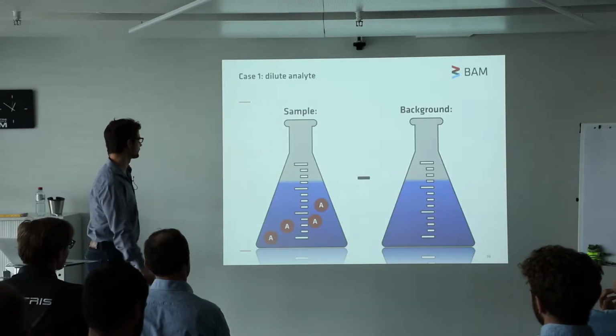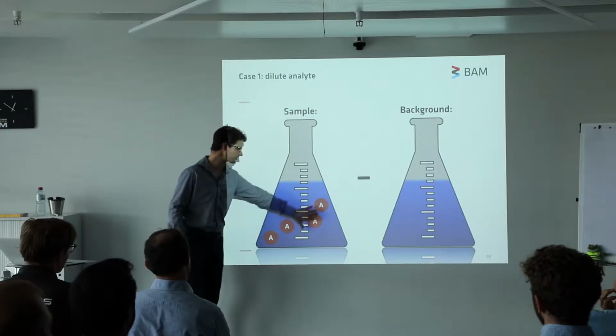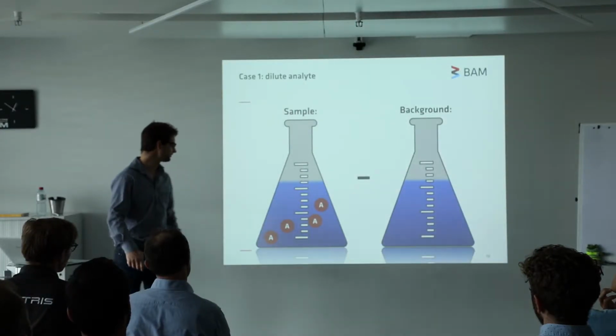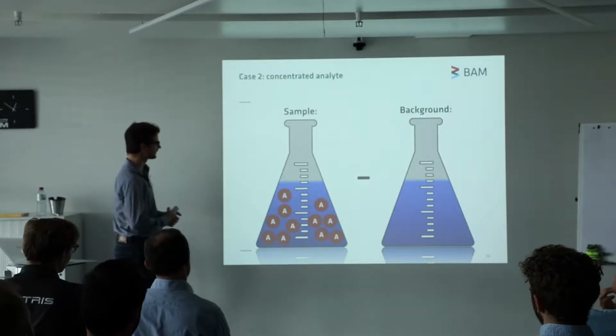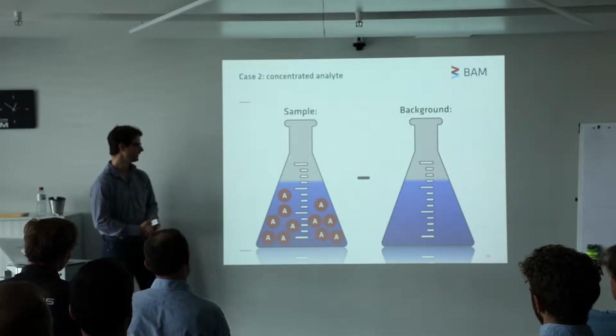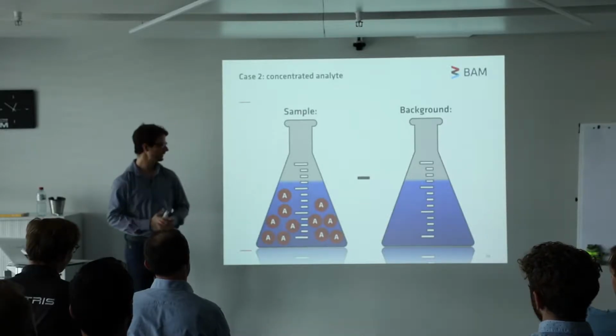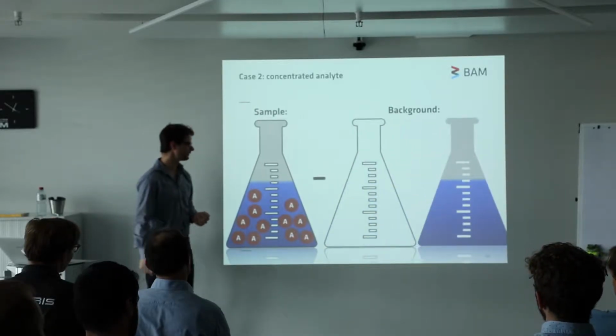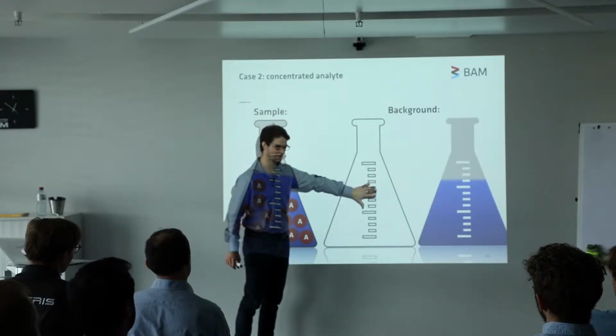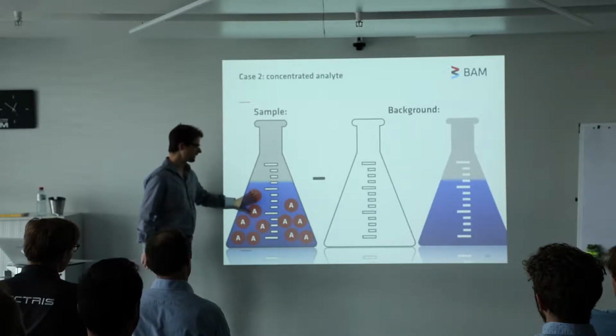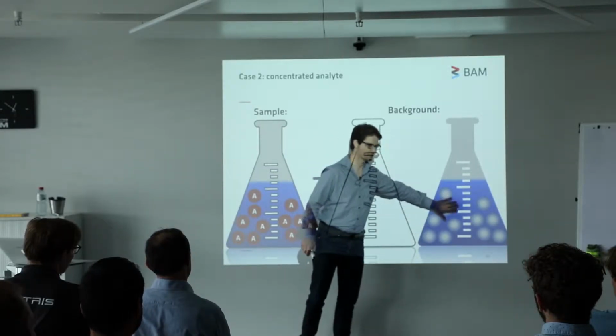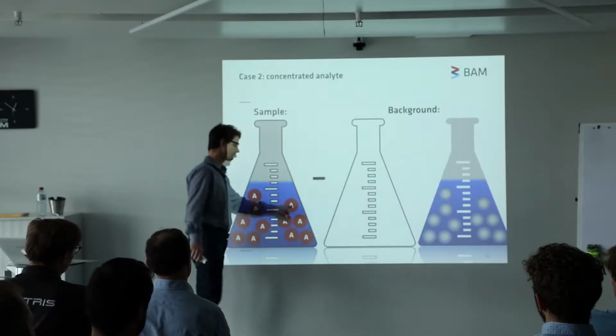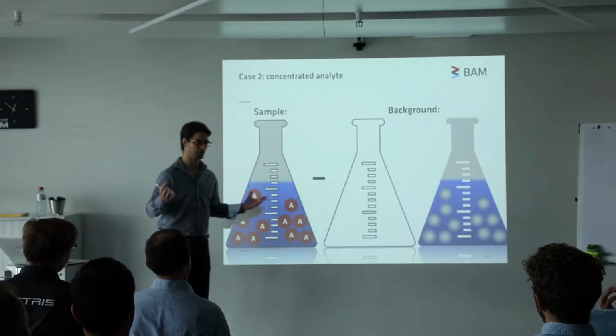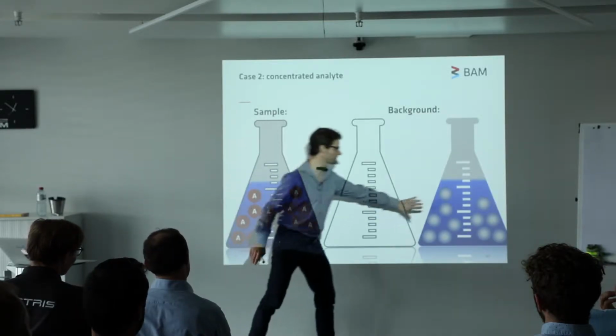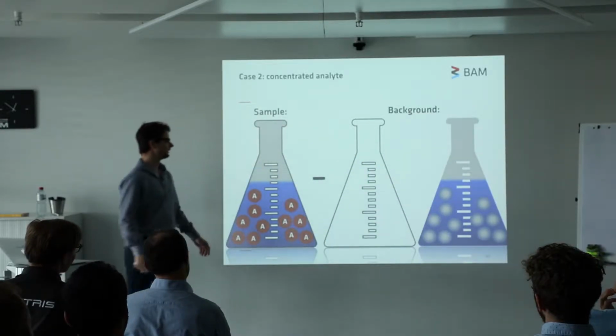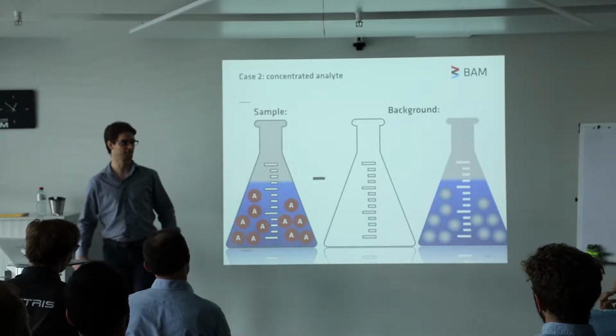However, to make it truly universal, we can't make this assumption. We can't make the assumption that the analyte is there in a low volume fraction, because especially geologists like to study things at high volume fractions, and that's where things get a little bit more tricky. In that case, you need to separate your background from the cell itself. That doesn't change. But the amount of background of the dispersant that you subtract has to be reduced by the volume fraction that your analyte takes up. Everywhere where your analyte is, your dispersant isn't, so you're not seeing that signal. And in this way, you can go up to very high volume fractions as well.